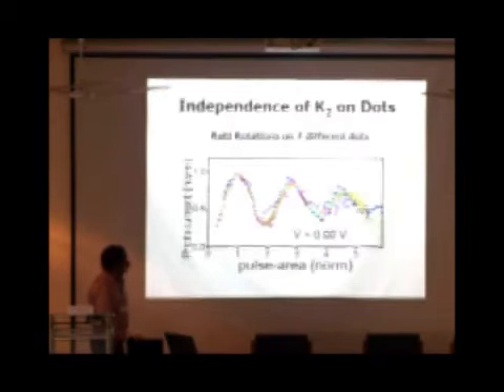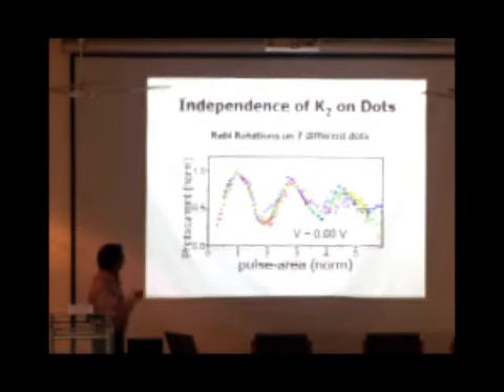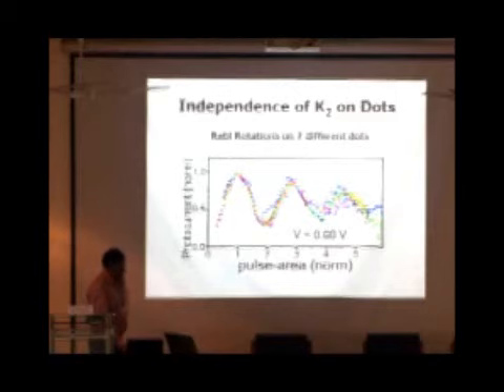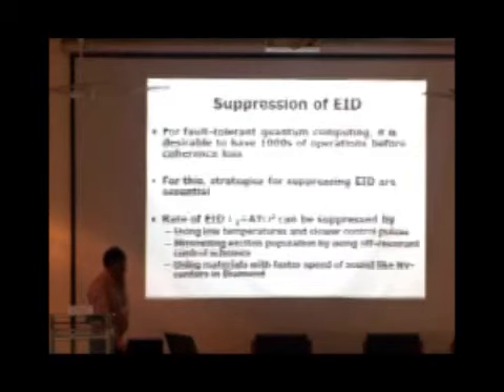As expected from the theory again, we did the measurements on 7 different dots, and there is not much difference in the Rabi rotations, showing that indeed this is dot independent.